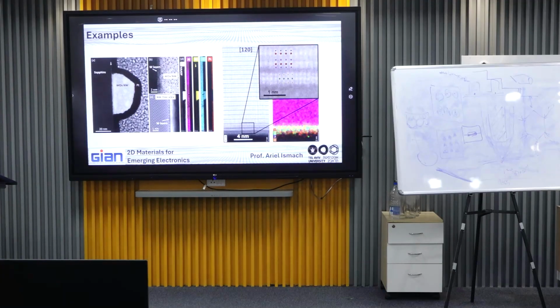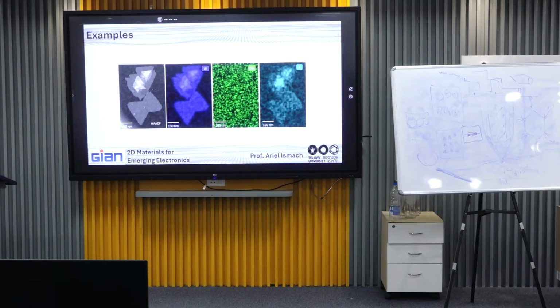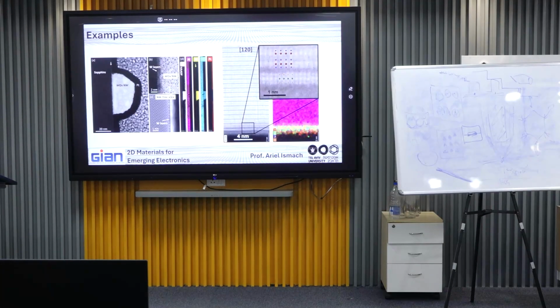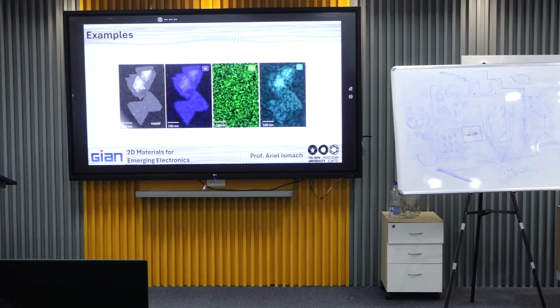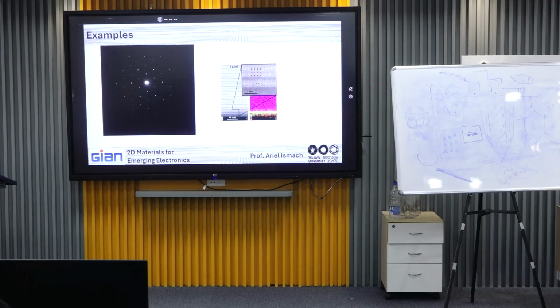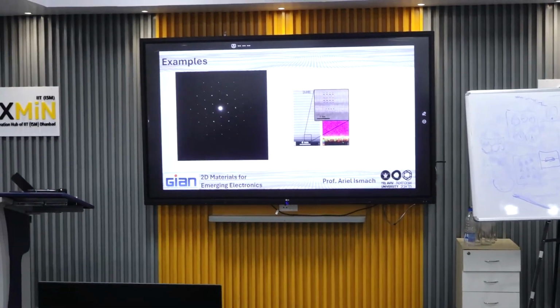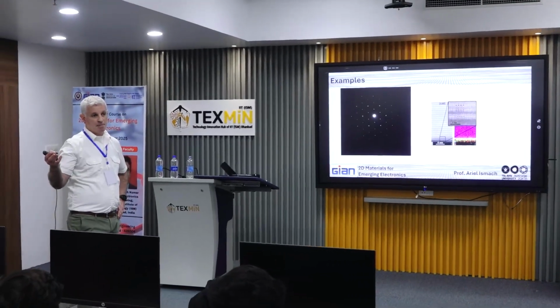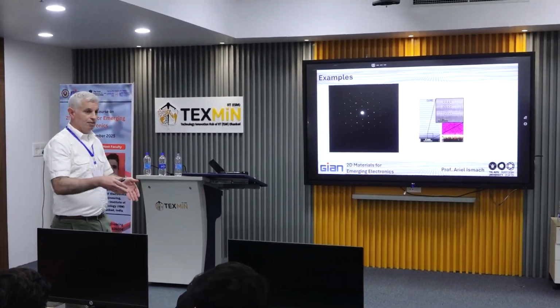Also, it requires some more. And lastly, EDS mapping, of course, gives you a lot of answers on the elemental composition of your materials, which sometimes, especially when you deal with heterostructures, is extremely important. And the important thing also is that you have the possibility to do electron diffraction. Electron diffraction gives you basically the same information that X-ray diffraction will give you on bulk samples, but in this case, it gives it to you on the nanoscale.